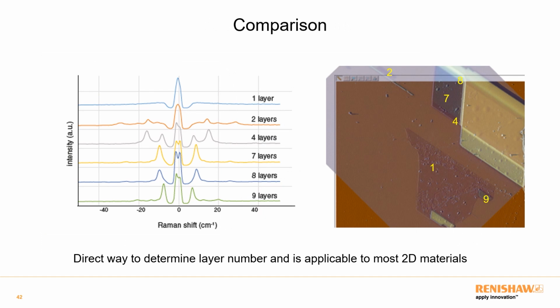So now I can use this correlated setup to measure the thickness of the rhenium disulfide at each position just by looking at the AFM image and measuring the topography, and I'm able to overlay it on the image. So I've got regions of 1 layer, 2 layers, 4 layers, 7 layers, 8 layers, and 9 layers on this particular region of the sample. At each of these points, I can tell the Raman system to take a Raman measurement, and I can then look at the spectra to see what's going on.